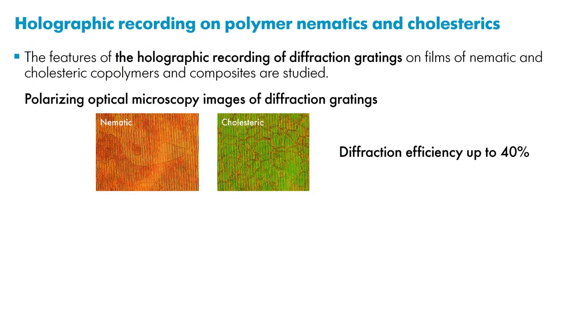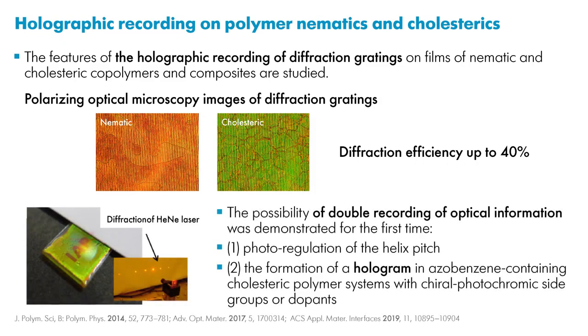Holographic recording on polymer nematics and cholesterics opens unique possibilities for creating various optical elements and for image recording. We have for the first time performed a comparative study of the holographic recording of diffraction gratings on polymer nematic and cholesteric films. Such recording was performed using a special setup by interference of two coherent laser beams. Relatively high values of diffraction efficiency were obtained, up to 40%. Moreover, the possibility of double recording of optical information was demonstrated for the first time.